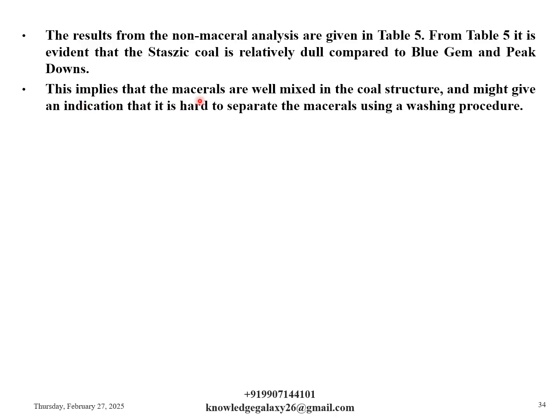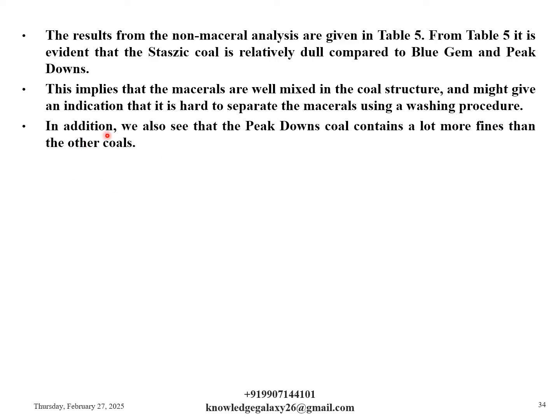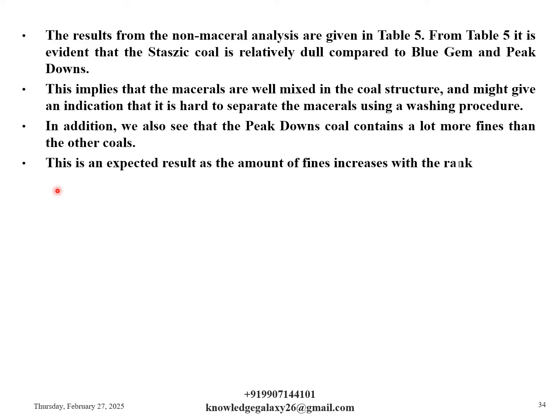From table 5, it is evident that the Staszic coal is relatively dull compared to blue gem and peak downs. This implies that the macerals are well mixed in the coal structure and might give an indication that it is hard to separate the macerals using a washing procedure. In addition, we also see that the peak downs coal contains a lot more fines than the other coals. This is an expected result as the amount of fines increases with the rank.